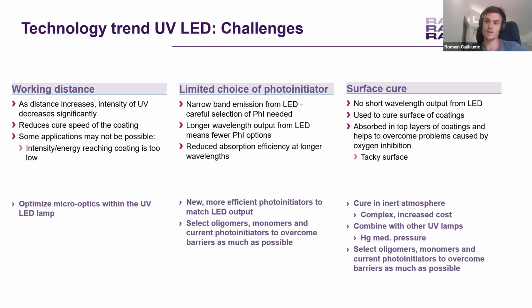To fight this, we can make some applications in inert atmosphere, but it's very complex, and it mainly increases the cost. We see lots of applications where we mix the two technologies, because both technologies, LED and mercury, have different advantages, and if we use them properly and mix them, we can have quite good applications. So we can mix, for example, an LED in order to cure very deeply, and then a mercury lamp in order to finish the curing on the surface. That could be a kind of mix where both technologies are used for a certain application.